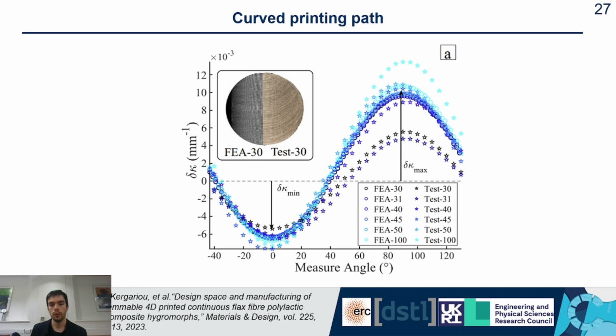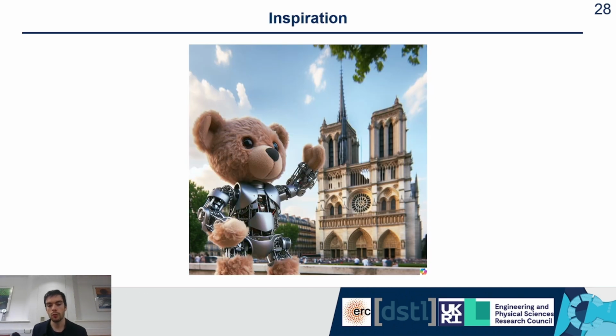So we've shown different ways of controlling the printing path, but as you can see on this specimen, the 30, by the way, means a radius of curvature for the curved fibers. The fibers are curved, but they're also very compacted onto each other. So we were wondering, can we disperse the fibers so that there is only a contact point between the first layer and the second layer, and maybe we can control actuation by doing this. So we took our soft robots on a trip to Paris, and in Notre Dame, as you can see in the middle, there's a sort of circular shape. We thought about this shape and tried to create something that represents that kind of circular flower shape.